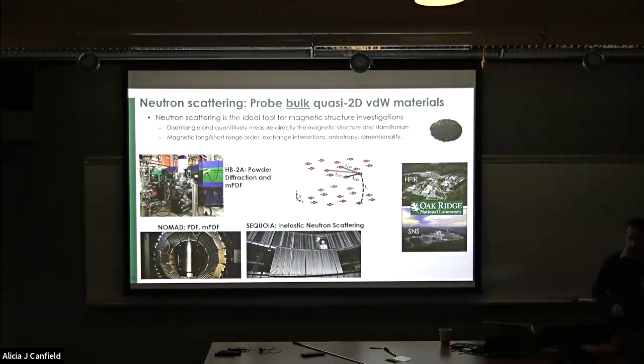So the probe of choice is neutron scattering. This really is an excellent tool for magnetic structure investigations. If you can do the measurement, if you have enough sample to do it, have the right technique, it's probably the best technique to get information on the microscopic magnetic information. The neutron interacts differently with the nucleus, with the charge, with the magnetic charge. So you can disentangle the magnetic information and you can extract quantitative information. So you can start to look at long and short-range order, exchange interactions, and dimensionality in the materials.